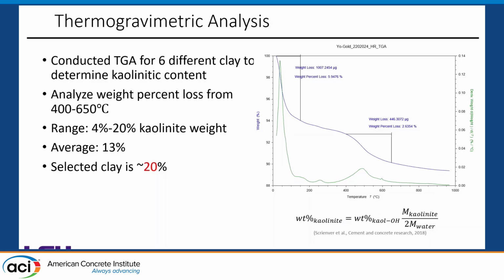During this process, there's an effect called dehydroxylation that happens, where water molecules come off of the kaolinite sample. We use the equation that you can see in the bottom right that shows that mass distribution and how you can transfer the weight loss into kaolinite present. We found a range of 4 to 20% kaolinite, which is rather low for LC3 clays, so naturally we chose the highest number, which was that 20% kaolinite present.